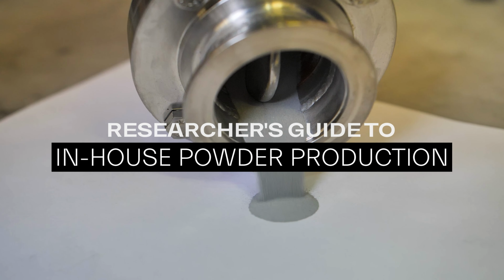One of the technologies very similar to laser powder bed fusion is electron beam melting. There, instead of a laser beam, an electron beam is used. The process is carried out in a high vacuum chamber while the powder is preheated to prevent warping and to reduce thermal stress. There are similar problems as in LPBF, so the powder has to be spread over the powder bed, but it's also vital to prevent the so-called smoke effect. If the electron beam hits the powder, it's being charged, and too small particles are very prone to be ejected from the powder bed. So preventing the so-called smoke effect is one of the main challenges in optimizing the electron beam melting process.